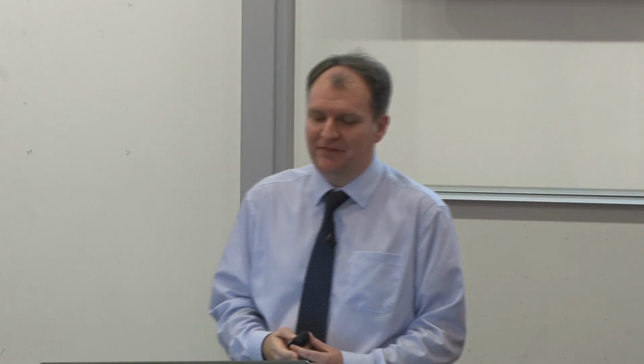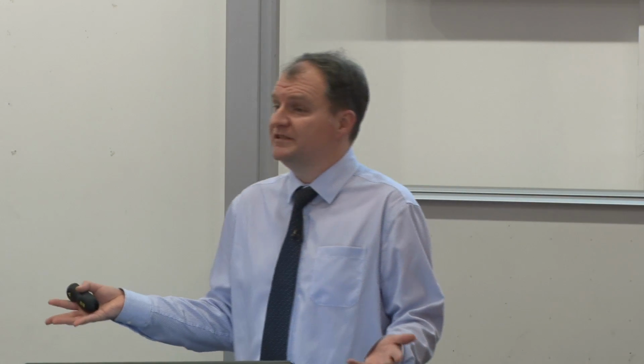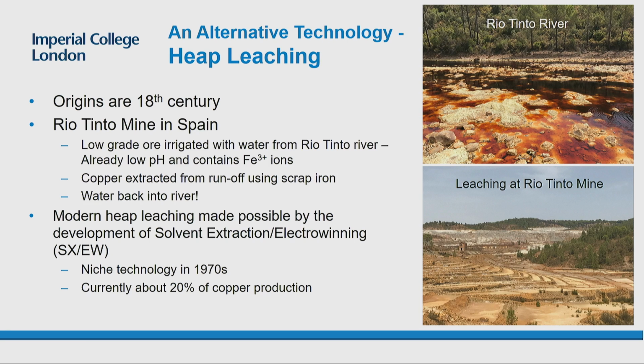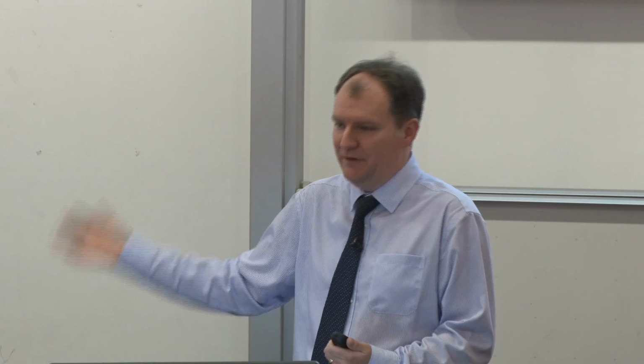Okay, but let's talk about the other technology. The alternative to flotation, or one of the alternatives, is heap leaching. Heap leaching is a pretty old technology in its origins. Something similar to heap leaching was carried out from the 18th century at the Rio Tinto mine in Spain. What they did was take the rock which wasn't of high enough grade for them to treat otherwise, and pile it into what look basically like rice paddies, in sets of ponds. Then they pumped water from the river up to the very top and let it percolate through all of these, and at the very bottom they put scrap iron in, and the scrap iron would cause the copper to come out of solution, and anything that wasn't would just flow over the back and back into the river.